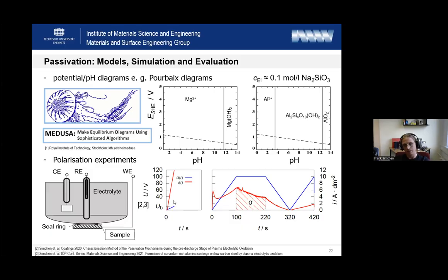If we improve our electrolyte, then step by step, maybe we can go to 60 volt, to 80 volt, to 100 volt. And anytime our passivation is good enough that we can carry out the complete measurement, and we can record the corresponding current flow. So we have here our voltage ramp. Initially, we have our naked metal, so we have an initial active peak.